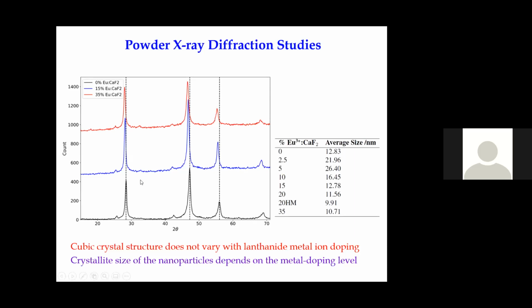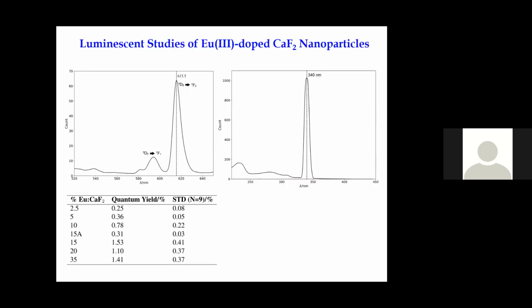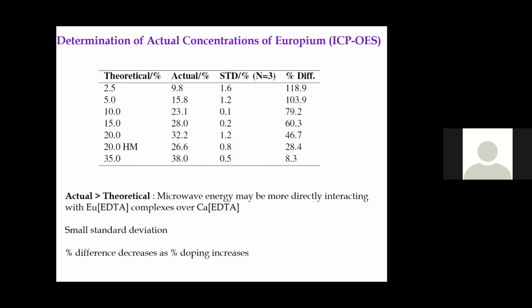In the XRD, you see when you increase the doping level, that means you are introducing more europium, the peaks are shifting slightly, but it is still maintaining the same crystal structure. The black curve is no europium, just calcium fluoride, but from blue to red, we are introducing a certain percentage of europium, and it's shifting a little bit, but we believe it maintains the crystal structure. Again, luminescence is shown, and we calculate the theoretical metal amounts by using digestion techniques like ICP, and you can correlate the amounts actually in the nanoparticle. Initially you see the actual amounts are higher than what we anticipated, but when you increase the percentage, it comes to the same numbers.